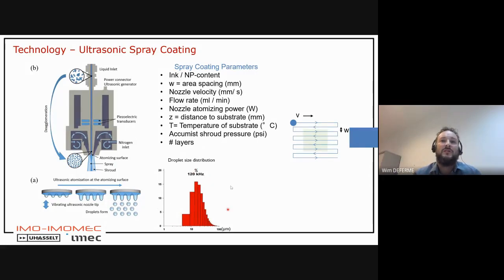So here you see the droplet size distribution for the nozzle we use, around 120 kilohertz, and they range, let's say, between 10 and 20, 30 micrometers, with a peak around 20 micrometers.